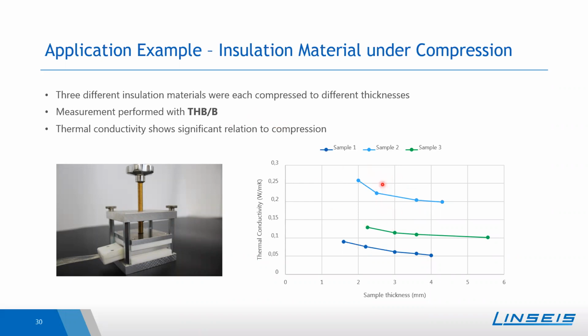From the results, one can see that all of the three different tested materials show different thermal conductivities. So from the values, you see that this is really an insulation material, and one can see that all show a significant dependence on the sample thickness, so a significant dependence on the compression of the material. So these are two application examples which I wanted to show you.